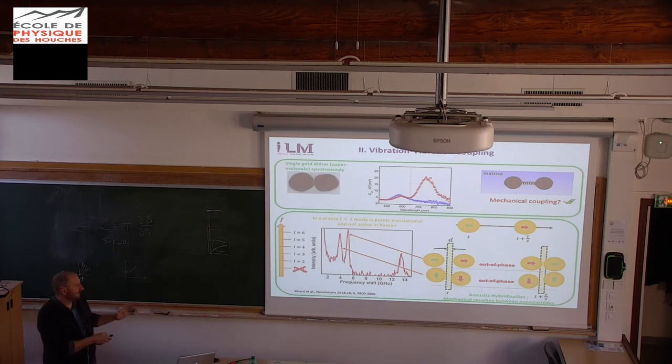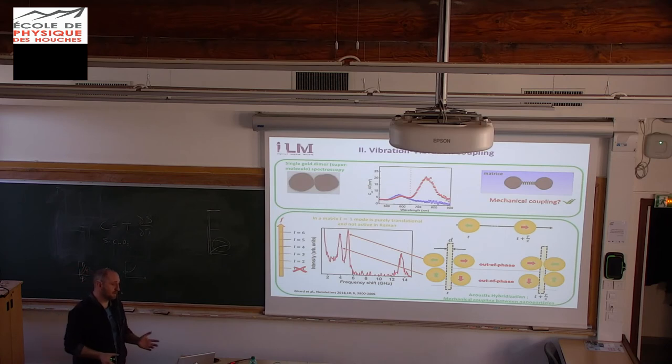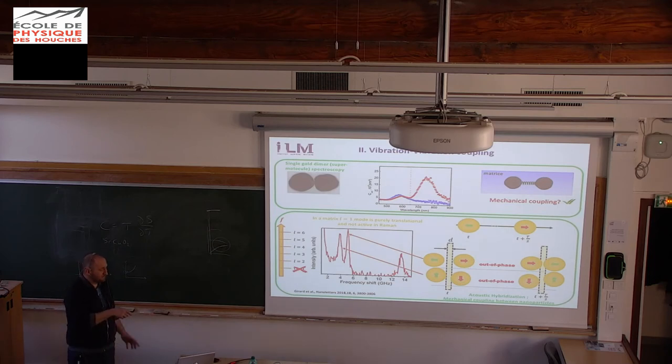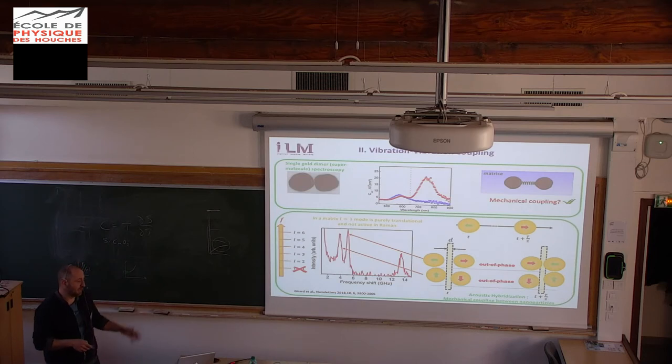Yes, that's right, all the modes exist. I only show this out-of-phase mode because it fits our results. The reason is also that if you consider the in-phase mode, it's again a translation. There is no Raman activity in theory, so we will not be able to detect it. We think that we should detect it because you will have a small modulation of the plasmon gap, but the intensity will be lower. And maybe there are other things that we are not resolving here.